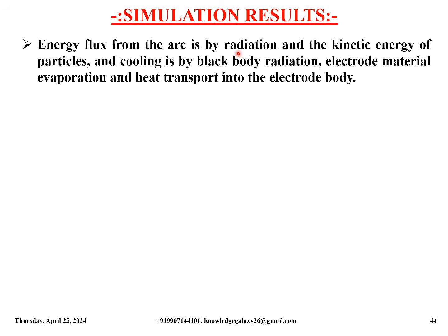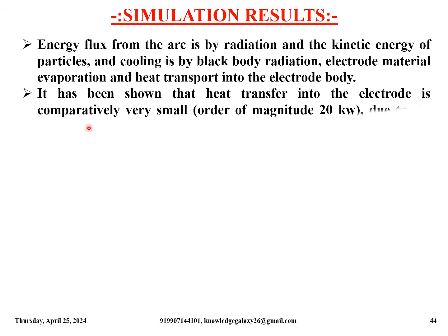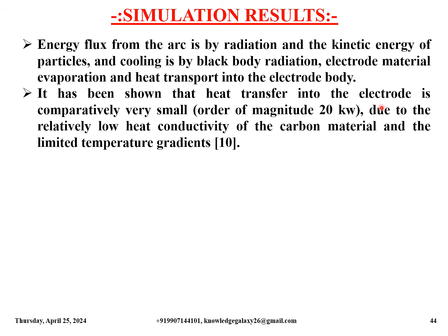Energy flux from the arc is by radiation and the kinetic energy of particles, and cooling is by black body radiation, electrode material evaporation and heat transport into the electrode body. All these simulation results are based on the figures I just presented in the previous slides. It has been shown that heat transfer into the electrode is comparatively very small, of the order of magnitude of 20 kW, due to the relatively low heat conductivity of the carbon material and the limited temperature gradients.